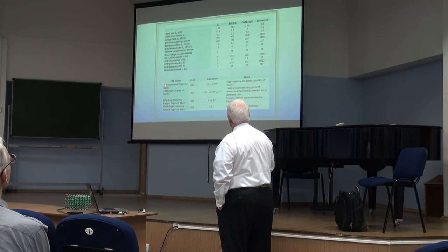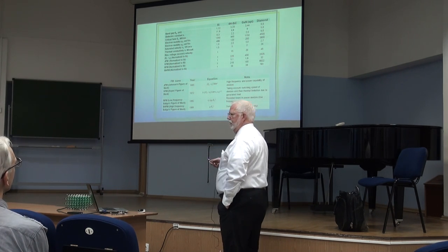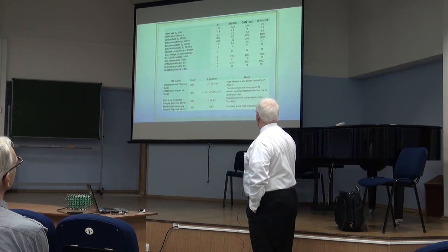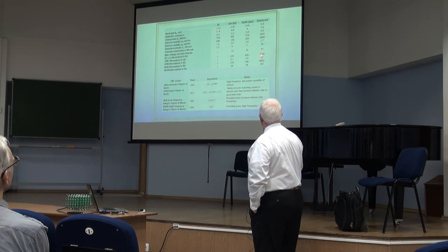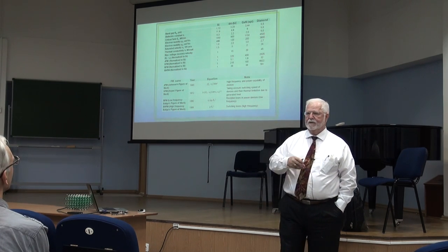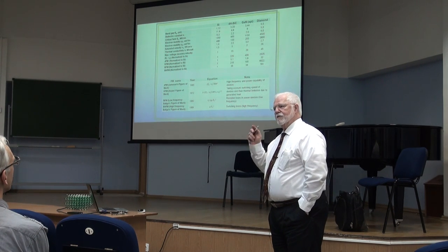The other thing that we plot here is the figures of merit. These are combinations of these properties that tell you how well a semiconductor performs in a particular type of electronic device, and that's described here. And if you normalize everything to silicon, what you see is that diamond just blows everything else out of the water. Diamond is probably the best semiconductor, or as a friend of mine said, it's the second best semiconductor, vacuum being the best.